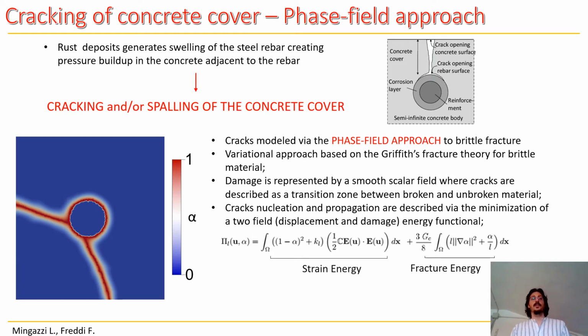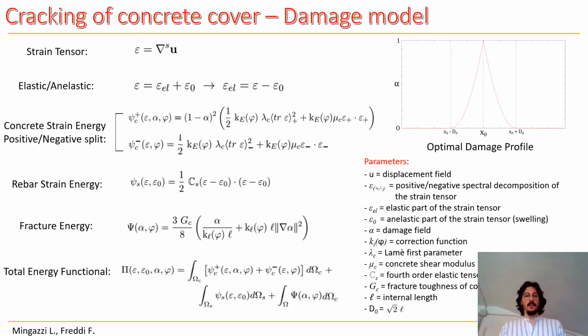In particular, crack nucleation, formation, and evolution is described via the minimization of a two-field energy functional, which depends on the displacement field and on the damage field. In the phase-field model we use to describe the formation of cracks within the concrete cover, we considered a traction-compression energy split for the concrete strain energy, allowing us to apply the damage field and the evolution of damage only in the areas under traction condition. For the steel, for the rebar strain energy, we consider only the elastic part of the strain tensor. This permits us to introduce the swelling obtained from the corrosion process as a loading parameter.